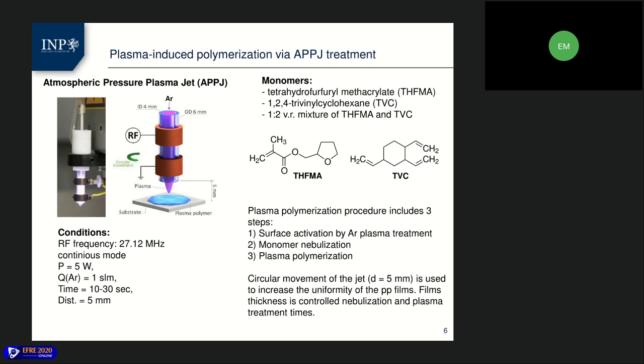Circular movement was applied to increase thickness uniformity of the deposited layer, and the process itself included 3 steps. First was the surface activation by argon plasma treatment, then monomer nebulization, and then plasma treatment of the liquid monomer film until the formation of the film was complete, which is the plasma polymerization step. Plasma polymerization time varied from 10 to 30 seconds, depending on type and amount of monomer.